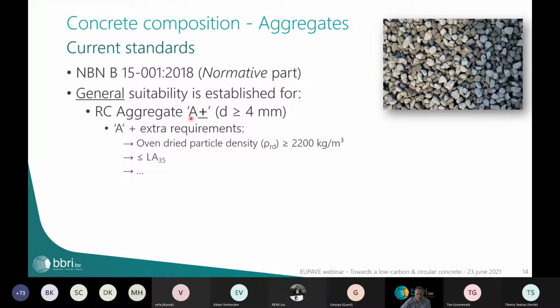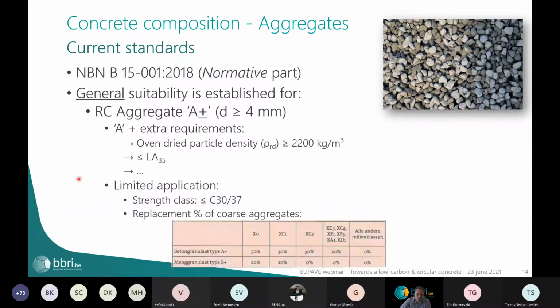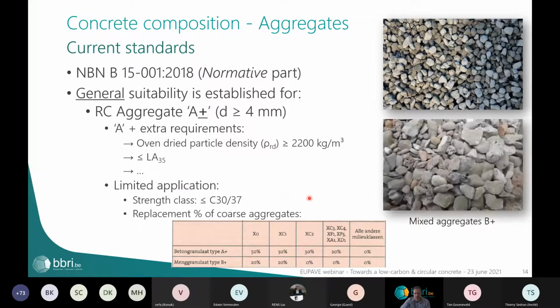So in Belgium we go a bit further than the requirements for the A aggregates, mainly for the oven-dried particle density and the Los Angeles coefficient. So the general suitability is established, but we cannot put these aggregates into the concrete however we want. It is limited to strength class C30/37, and the replacement percentage of the coarse aggregates is limited to some very limited percentages. So in fact you can use them, but the application is still very limited. But there are already concrete plants that can deliver concrete following the standard with recycled aggregates.